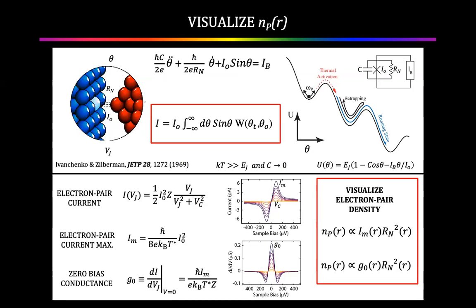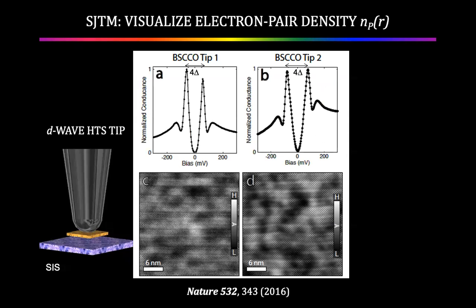The trick we had to deal with is to drive up the junction resistance so we could make an image, while maintaining the Josephson critical current as high as possible and keeping the temperature as low as possible. So we did that by building a millikelvin STM, where the operating temperature is about 50 millikelvin, and making the STM tip a high TC tip by exfoliating a tiny little piece of BSCCO onto the tip. And we can tell that this has succeeded because we can measure the single particle spectrum, and now the separation between the peaks is 100 millivolts, which is 4 delta, not 2 delta. So 2 delta from the tip and 2 delta from the sample.